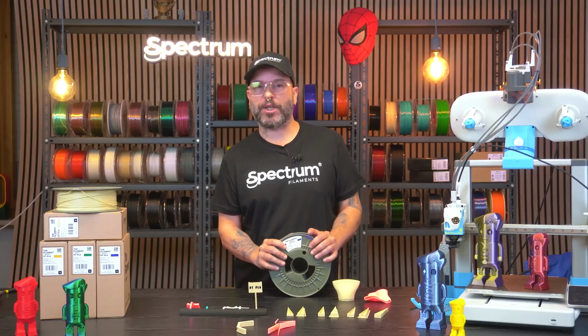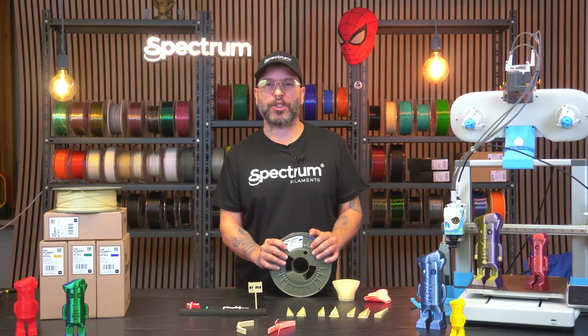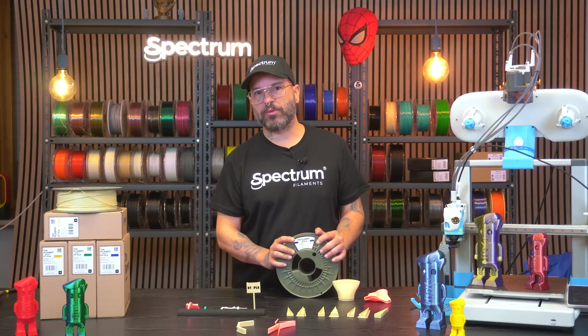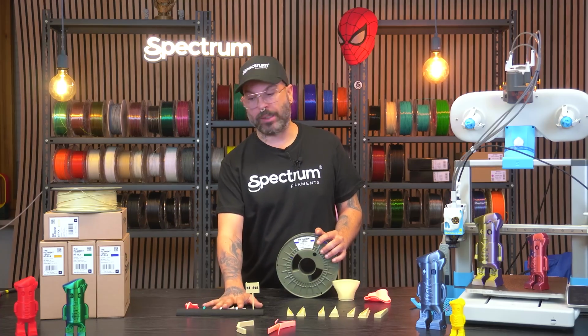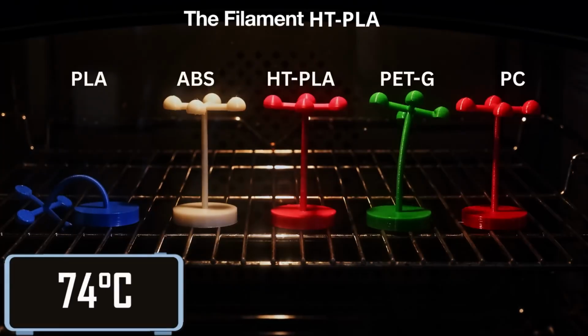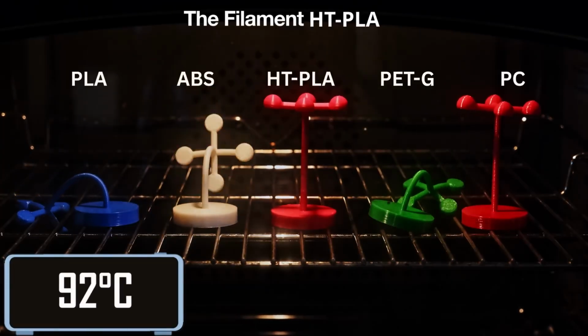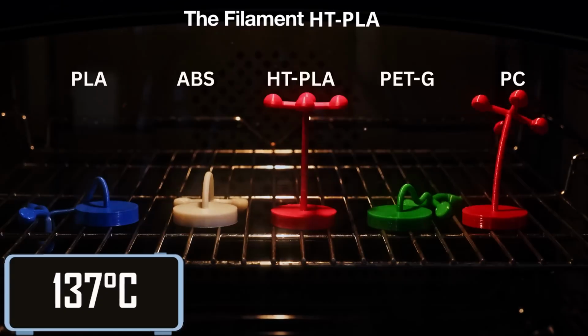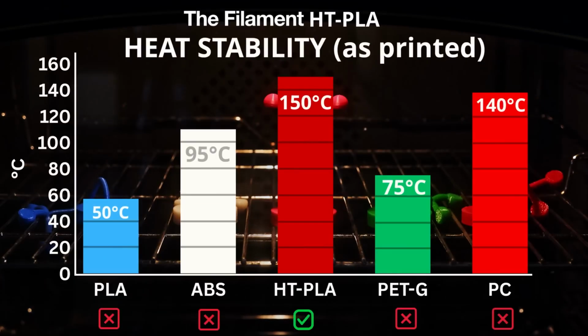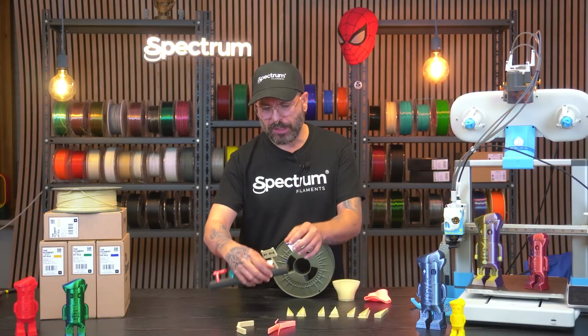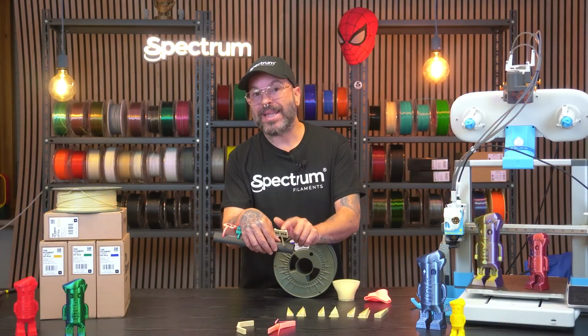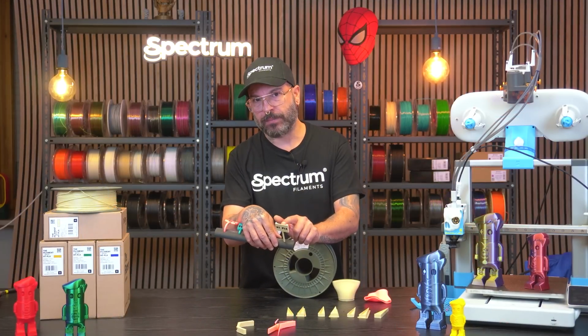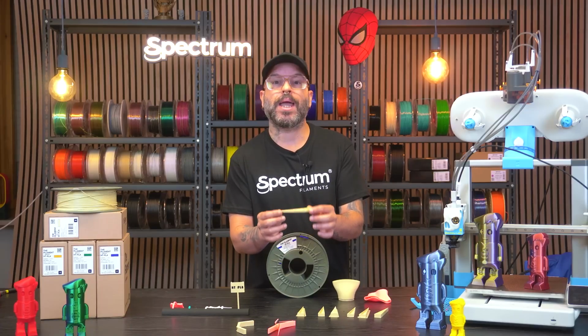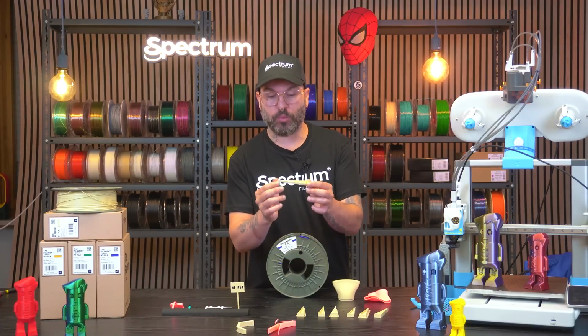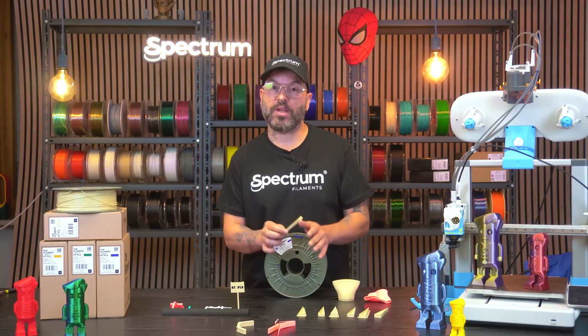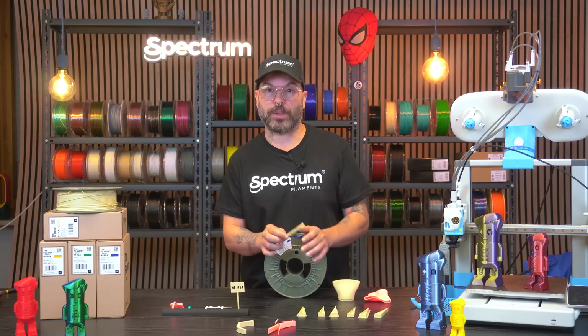And there you have it, our new filament, the Filament HT-PLA. The tests were really successful, especially the one compared to the other materials. We saw the cascade from PLA, PETG, ABS, PC, and finally we still have the HT-PLA standing right there. We have maybe just a little bit of melting, but that's due to the infill of the actual print. And after that we saw the warping issue that we have with the standard PEI sheet with no brim, with brim, down to 35 degrees with the Bambu Lab Cool Super Tack build plate.